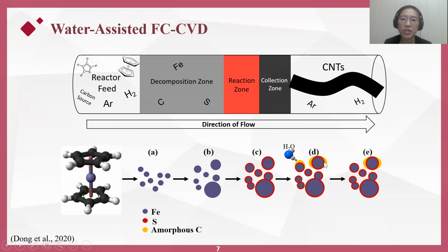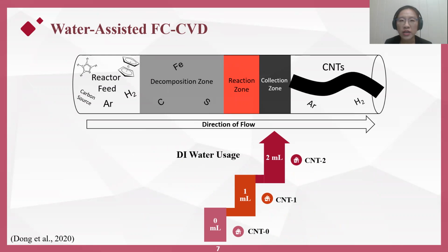Amorphous carbon, shown in orange here, is generally considered a major byproduct in hydrocarbon pyrolysis, and its deposition on the catalyst particle surface renders them inactive. Water selectively reacted with the amorphous carbon, and the coating removal revived the catalyst activity and elevated the synthesis efficiency. Additionally, smaller size CNT could be achieved as a result of the catalyst size shrinkage. In this work, we included deionized water into the catalyst solution to provide a more homogeneous and uniform distribution. Based on the amount of water added into the standard catalyst solution, 3 groups denoted as CNT0, CNT1, and CNT2 were investigated in the later sections.